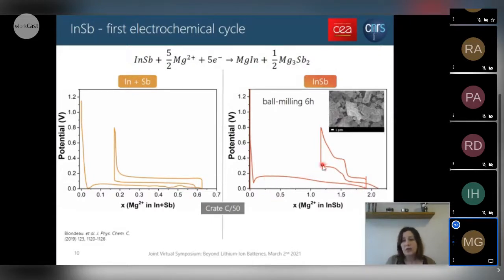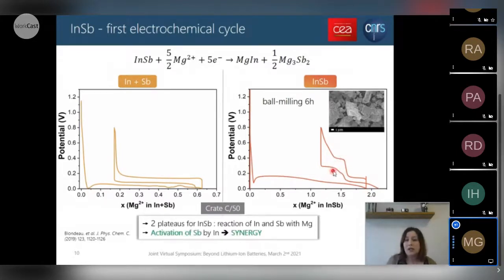So the first region is in fact associated with the reaction of magnesium with antimony to form the Mg3Sb2 compound, while the second plateau is linked to the formation of MgIn. What is really interesting here is that this first plateau, corresponding to the formation of Mg3Sb2, we can see in magnesiation and in demagnesiation, showing that the reversibility of antimony is present, and that we indeed activated the reactivity of antimony when we combine it with InSb.